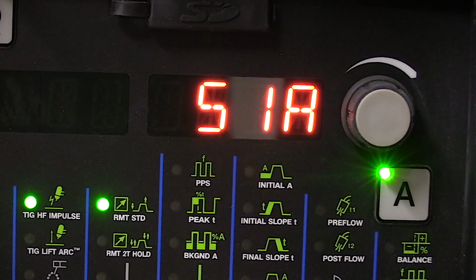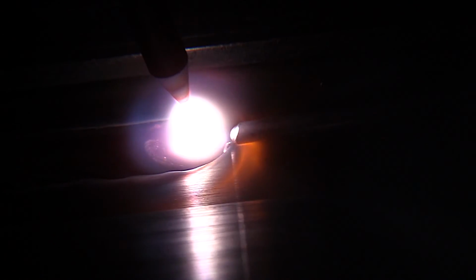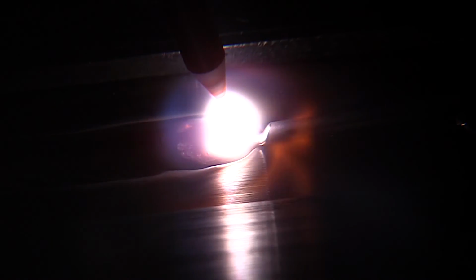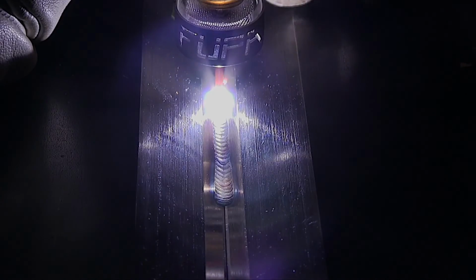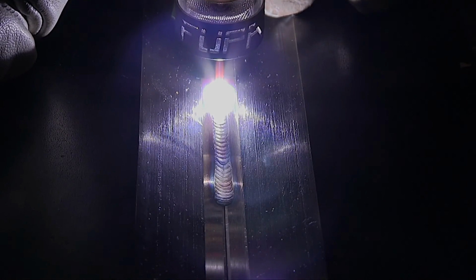51 amps it takes to penetrate this stuff. That was what I settled in at. It would probably take a little bit less than that if it wasn't such a chill block. Anytime you put something in a fixture that's a heat sink or a chill block like this, it's going to take a few more amps to weld than it would be out in its free state. But you have to have something to hold it down and keep it straight, and a fixture like this is very common in the industry.